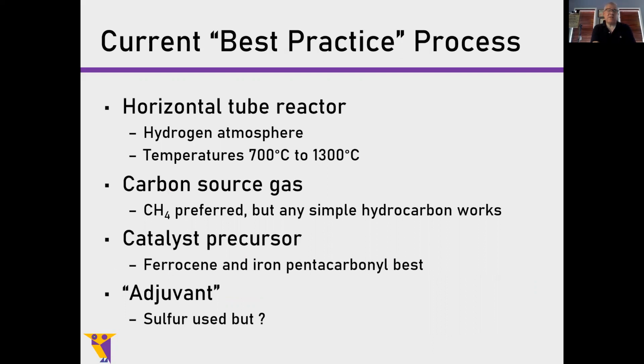I have made it out of pesticide. Any carbon source material will make nanotubes of varying quality. There's a catalyst precursor. So typically the catalyst itself is not created ex situ. It is fed in as an organometallic compound. Ferrocene and iron pentacarbonyl are nice because the iron is already in a zero valent state and will therefore condense from an aerosol into particles that can grow the tubes.